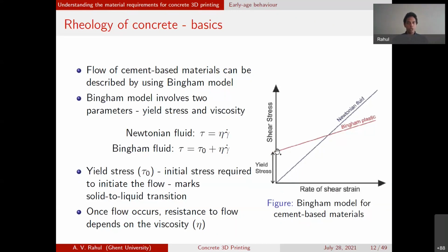But if you do this in the case of a material like concrete, you will see that you end up with a non-zero y-intercept. And the non-zero y-intercept, which we call tau zero, is called the yield stress of the fluid. Mathematically, it shows a difference in the graph, and it shows a difference in the equation that represents the fluid. So in a Newtonian fluid, you have a zero y-intercept, and for a fluid like concrete, which we call a Bingham fluid, you have a non-zero y-intercept, which is due to the presence of yield stress.